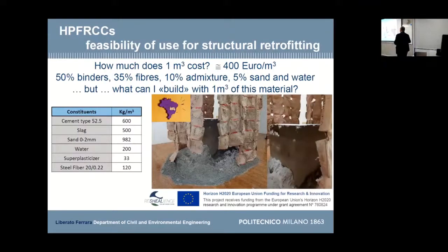This was just to recall once more the idea of the cost per cubic meter. Well, probably this 400 euros per cubic meter is now even a low estimate because of the change in prices. But see, 50% of the cost comes from the binders. This is a typical mix design. And 35% of it comes from the fibers. The rest is the admixture, which is quite important. You see, it's 3% of the binder content. It's a huge quantity of admixture. If you go to a normal concrete, you have 1% of cement as an average. But this is just to comply with the requirements of the mix design.